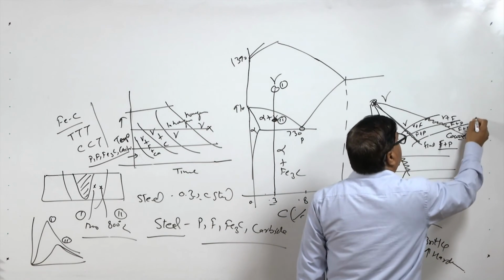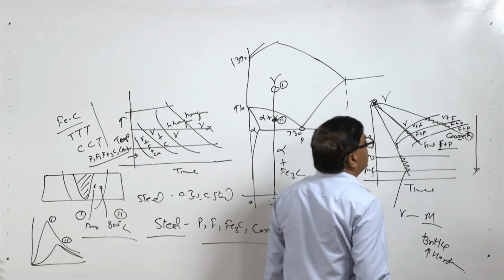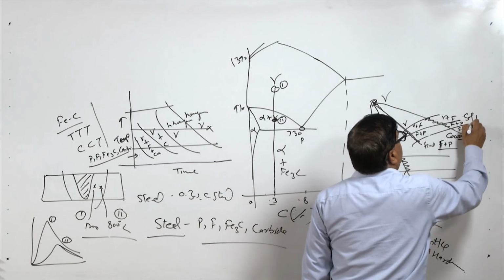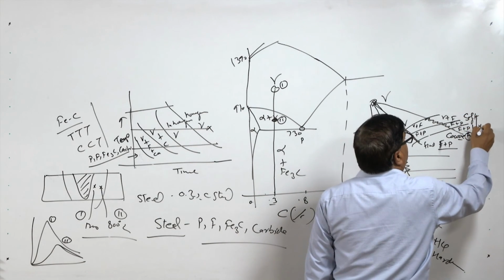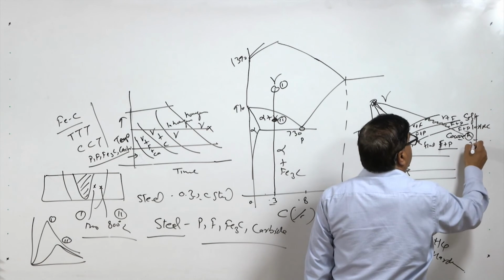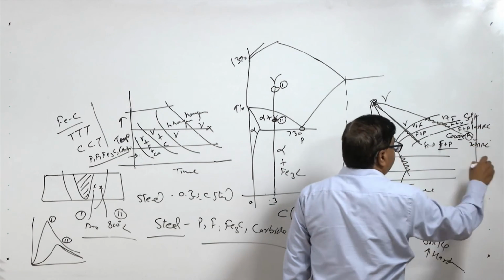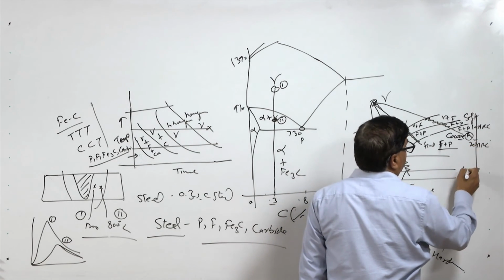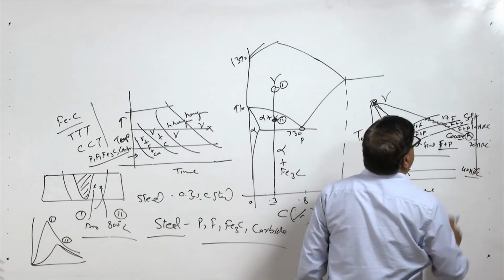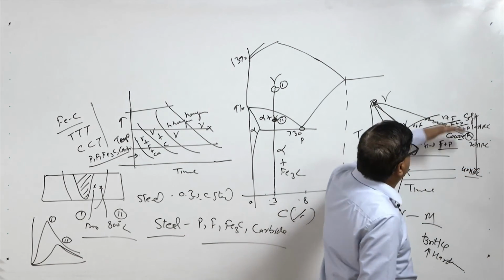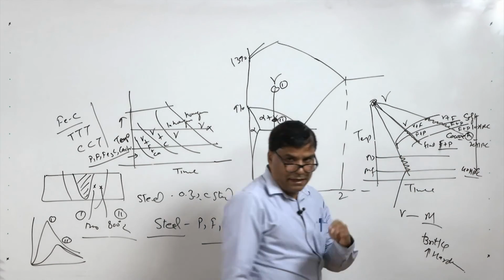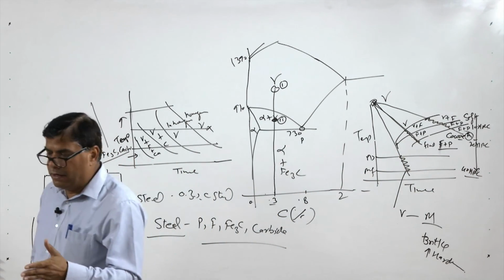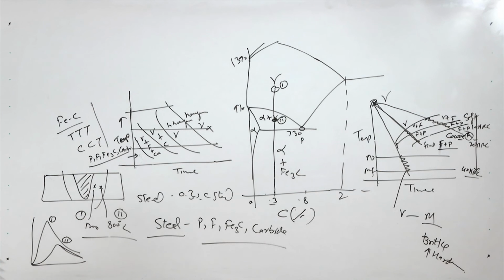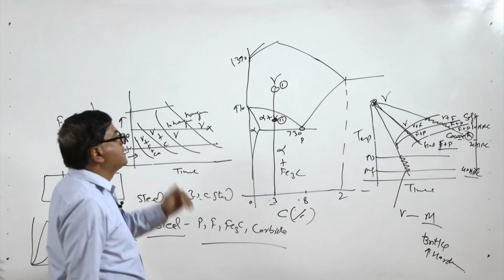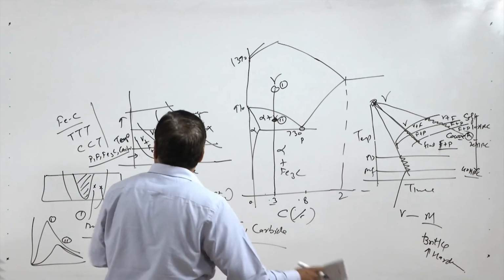In this diagram, this will be the trend of increasing hardness. Initially we get soft structures, like say 10 HRC, 20 HRC, and after hardening we may have say 40 HRC. As the cooling rate increases, our hardness keeps on increasing, and this happens due to the structural transformation from austenite to martensite, and at the same time the grain size refinement is also affected. So, this is how we can relate